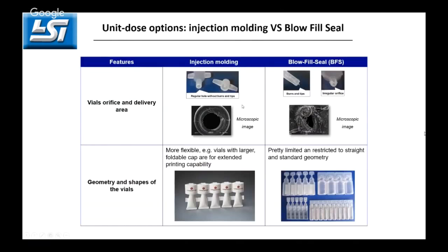The microscope returns images of the orifice of an injection molded vial that are consistently clean. Delivery areas of blow-fill seal vials show less consistency from vial to vial, with the possibility that the droplet size could vary. The mold of an injection molded vial allows for some flexibility in meeting customers' requirements on shape and geometry. For example, it is possible to make a foldable cap to print or label more information on the vial. Blow-fill seal is more limited to this extent, without many options out of the traditional straight geometry.